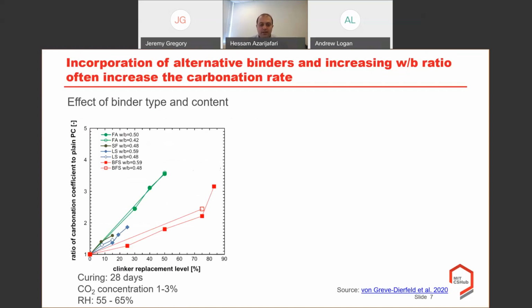Here on this graph, you can see that on the y-axis, we have the rate of carbonation coefficient relative to plain PC. When it is 1, it means that it equals the rate of carbonation coefficient that the plain Portland cement without any pozzolanic materials or alternative binder has. And on the x-axis, you can see the clinker replacement level from 0, obviously, up to 80%. And each curve and each dot represents one type of alternative binder or supplementary cementitious material.